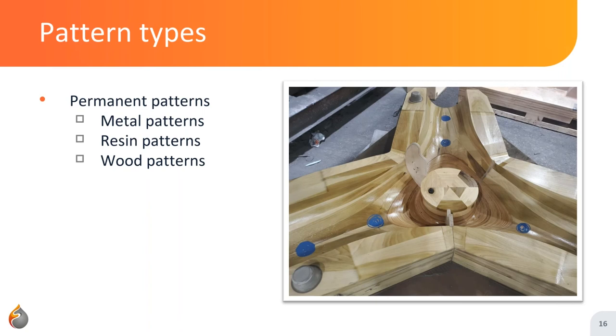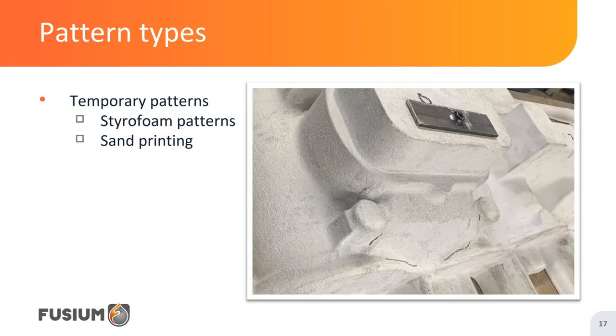At TMA, our magnesium foundry, we often fabricate parts that are six feet long but only one-sixteenth of an inch thick — the smallest variation leads to scrap production. Resin patterns really shine for those productions where pattern stability is critical. A wood pattern can easily cost over $10,000 for a $2,000 casting — if you only want one casting, your $2,000 casting costs $12,000 with a wood pattern. Foam patterns are a great fit when you need no more than a handful of castings, especially if they're not too intricate — your $2,000 casting might cost an extra $2,000 to $3,000, much better than $12,000.